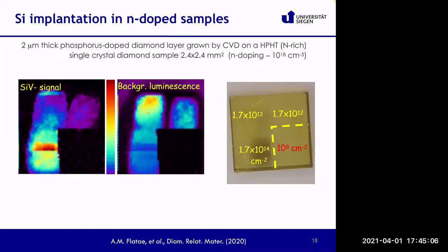And we went on by trying to generate the single photon into a conductive diamond sample. So instead of creating a PIN junction, we thought, okay, can we simplify these systems and get only, you know, one type of conductive sample? And we decided to go for N-type diamond, which is obtained by using phosphorus. And then here the problem starts. So you see here a diamond sample that has been implanted with different fluencies of silicon ions, 10 to the 14, 10 to the 13, 10 to the 12, and 10 to the 8.